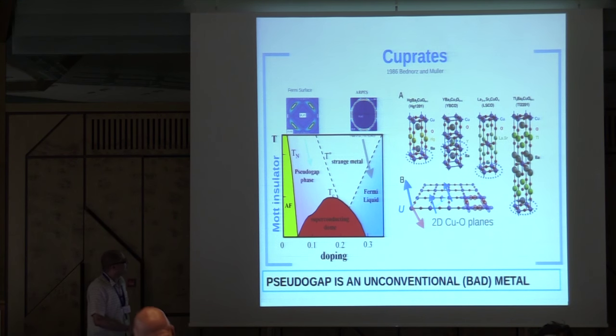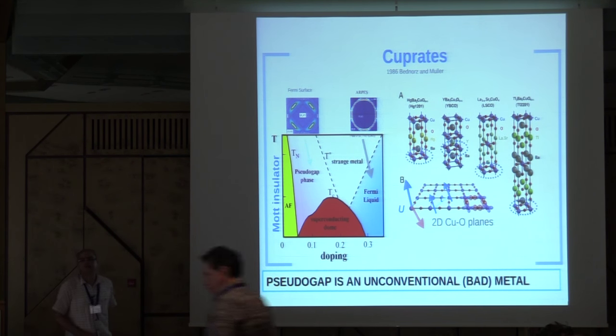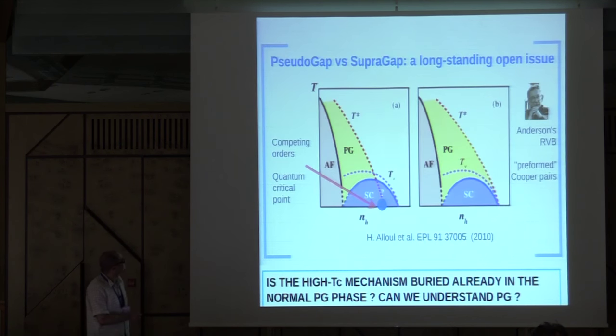Okay, we are talking about cuprates, the phase diagram rather rich. Superconducting phase, high temperature, and the pseudogap phase that we have seen is a good metal, perhaps, but is still unconventional. In this sense, I will say bad metal, with the Fermi surface that breaks into pieces. So for my student that was asking me before, these regions here are called hotspots. And the nodes, conversely, are called cold spots, because hot, you have a high scattering, you lose the Fermi surface. As you can see here.